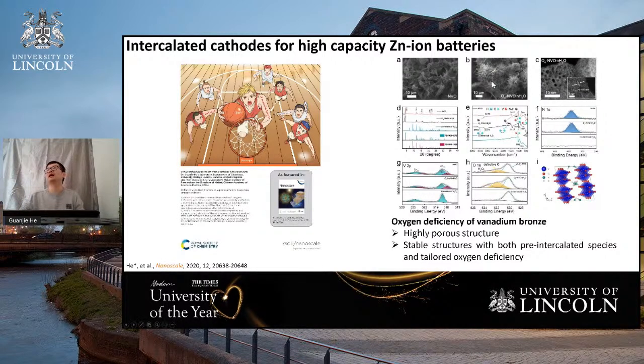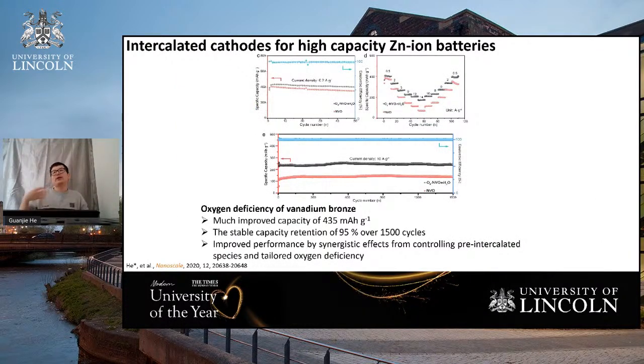And you can see from the electron microscope structure, just from the one-step synthesis, we can make those porous structures. So that means cathode materials can have a good interaction with electrolytes, the species in the electrolytes. And so these materials can work quite stable as a zinc cathode. We showed a much improved capacity of 435 milliamps hour per gram. And so also compared to the first works, the rate performance increased a lot. And you can also realize the stable capacity retention. That is over 95% over the 1,500 cycles.